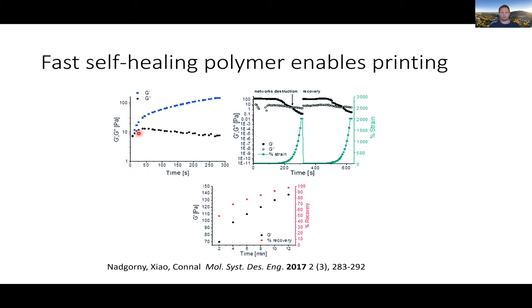So you need to have, well, I guess this is actually probably more about self-healing, sorry, but we're using the rheometer to look at this. I think this figure shows it probably the best, where basically you're shearing the rheometer, so putting a lot of shear on this, and then we essentially put as much shear as we can until it actually breaks. The network is breaking here. And then what we do is just let it sit on the rheometer, and after a certain time it's recovered, and we can then remeasure these materials.